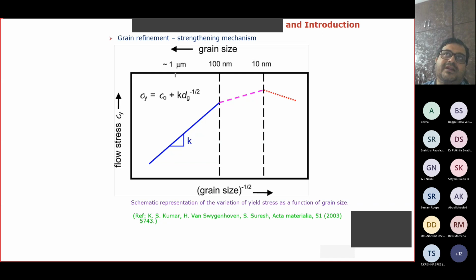Here k is the Hall-Petch constant or locking parameter, and the value of k will tell you whether the grain boundaries are strong enough to contribute to your strengthening or sometimes they could be weaker as well, and that gets reflected in this number k. And sigma naught is the lattice frictional stress, that is the resistance offered by your crystal material to a moving dislocation. After all, in your periodic table, when you look at different materials, whether they are BCC or FCC or HCP or any other crystal structure, you see that some are hard and some are soft. And this originates from the fact that a moving dislocation will have a lot of resistance in harder materials, or relatively less resistance in softer materials.